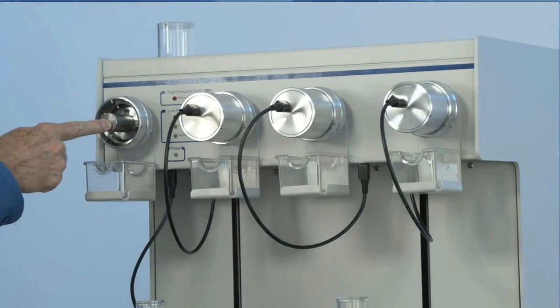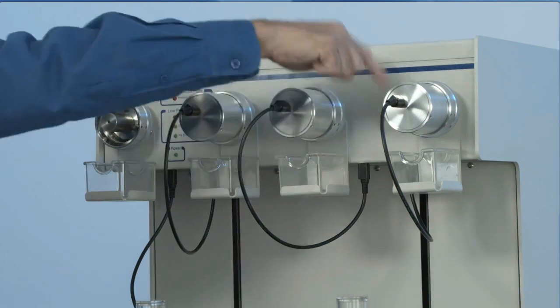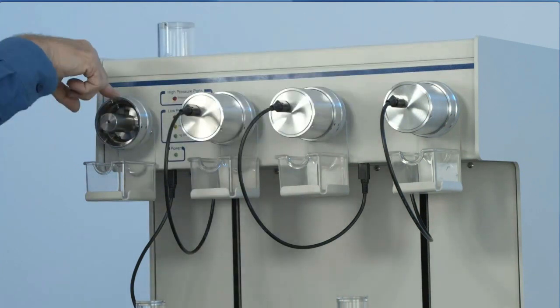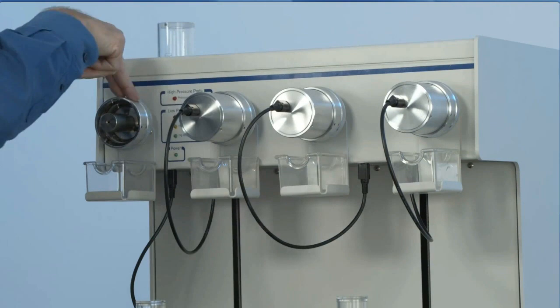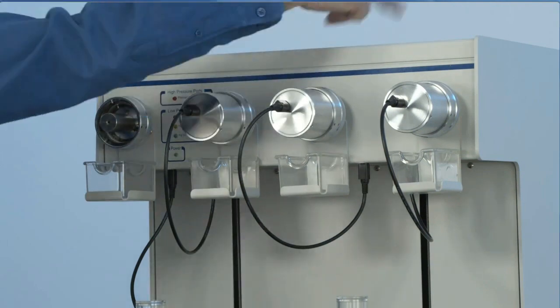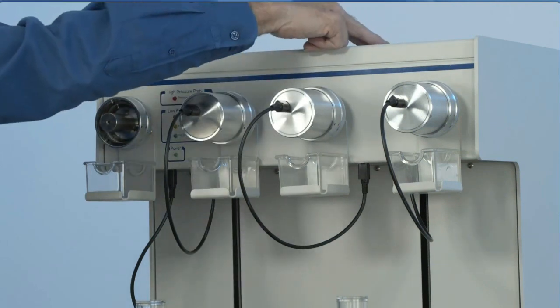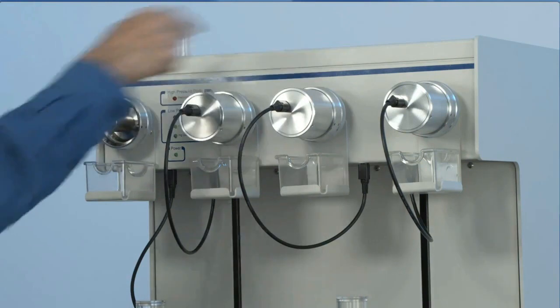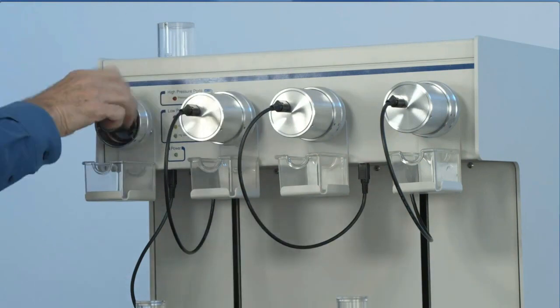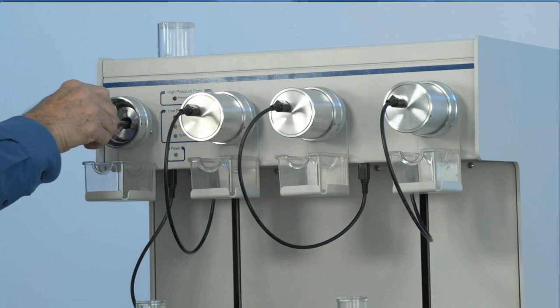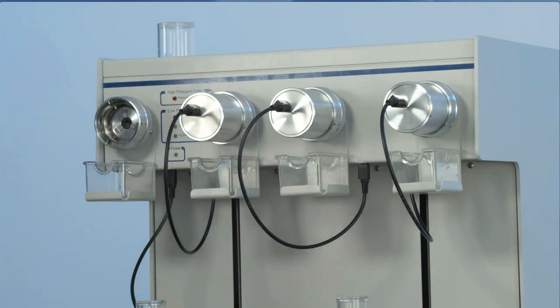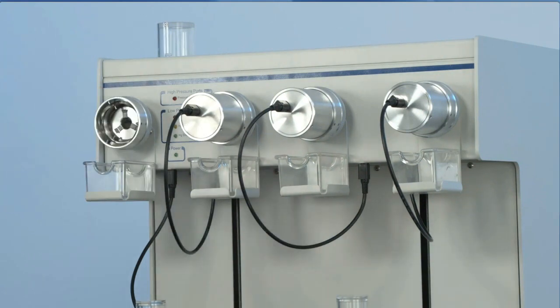You'll notice this filler rod here. All of these will have rods in them if I'm only going to do one analysis, because I have to analyze one sample because I have to be able to seal the system under vacuum and under pressure. So when a penetrometer is not in one of these ports, you need this filler rod in place. The software can sense its presence, by the way. If you have an open port, it won't let you start a low pressure analysis because it knows you won't be able to evacuate. So we'll just take that out.